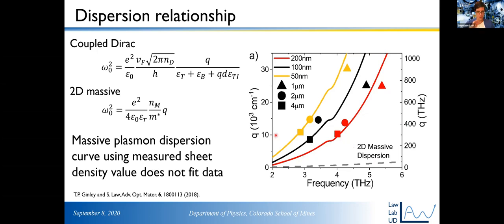Now, the question I get 100% of the time when I present this is, how are you sure that this isn't massive plasmons? These topological insulators are not perfect. They have some massive bulk carriers in them. And they may also have band bending at the surface to create a massive 2DEG. So to answer that, here's the 2D massive dispersion. It's the gray dashed line. It's using the same carrier density, the measured carrier density. And you can see it doesn't fit at all. It's so far away from our actual measured data.